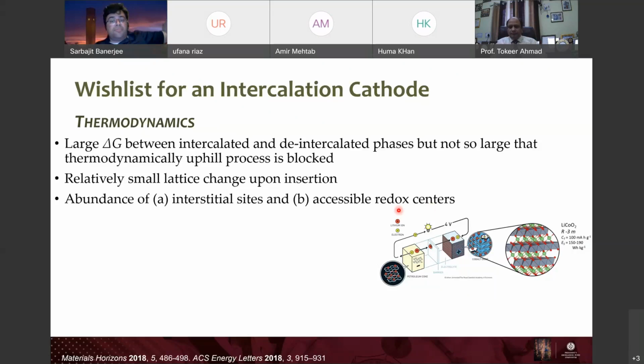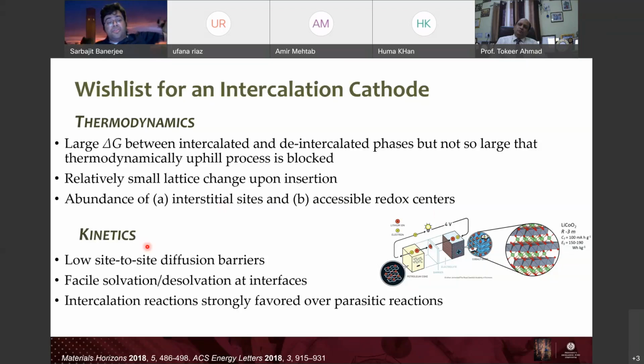And why transition metals? Because they've got multiple redox centers. So that's the second point. You've got to have accessible redox centers that you can reduce. So you're essentially doing energy storage through redox reactions at transition metals, right? For instance, if you're doing manganese chemistry, you're cycling through the different oxidation states of manganese, right? So thermodynamics is necessary but not sufficient. You also need kinetics, right? The ions, like I talked about, have to enter and penetrate through the bulk of the material, right? So we need to have low site-to-site diffusion barriers. The ions have to be able to move through the lattice.